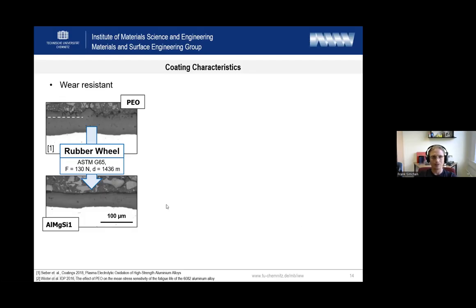And this we can discuss here on the slide regarding the coating characteristics. Here we see an example. We applied a rubber wheel test on a PEO coating, which was formed on such an aluminum magnesium silicon alloy. Usually this rubber wheel test is a really challenging wear test, but we see that we carried out rather a polishing. We removed the outer porous part, and the inside working layer of the PEO coating is basically unaffected. So we carried out rather a polishing step than creating any significant wear result.